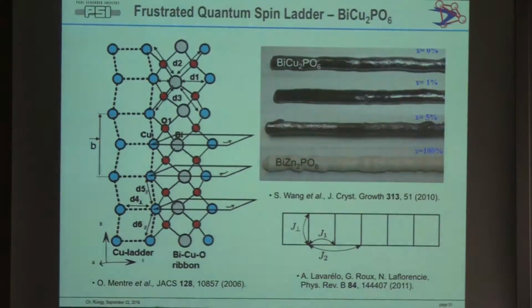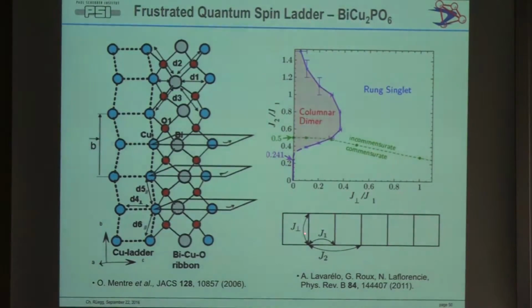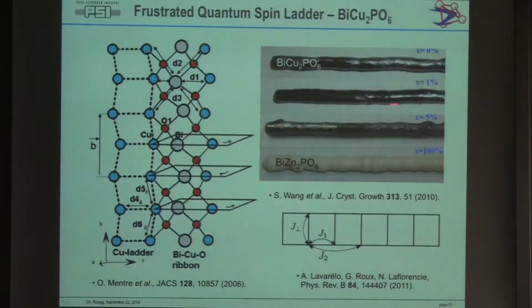Just as the very last example, just to say there are other materials. Now I don't have time to show this. So these are basically other ladder materials with a bit higher energy scales, and there you also have bulky crystals, which are actually closer to the strontium copper oxide mentioned this morning. These are grown with image furnaces. You can polish this, and this stuff you can actually just handle in a glove box, but that's a glove box you buy. It costs $50,000, and you put it in your garden. So you have to be very careful with machining, but this is possible. Certainly with this type of oxides, we can try many different things, polishing and stuff like that.